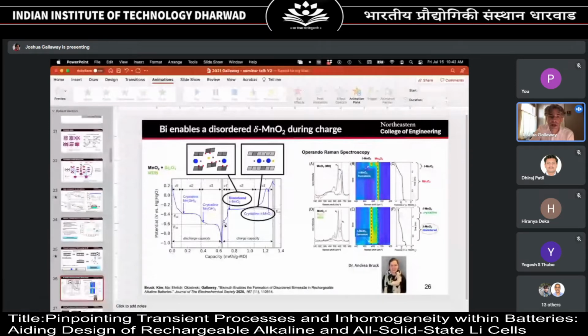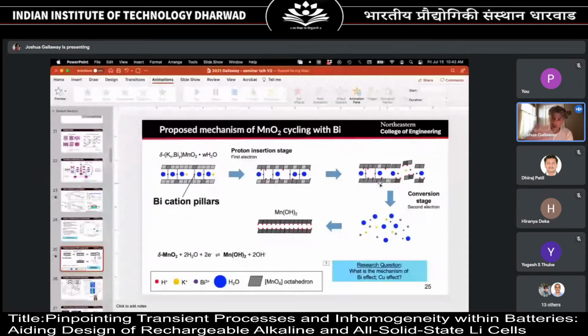So this led us to hypothesize, if I go back here, if we're going backwards through this reaction, the bismuth helps this structure form very quickly. And so this layered structure is present almost all the time through charge. And without the bismuth, it only forms at the very end. So perhaps the bismuth pillars this structure and helps it form very early.